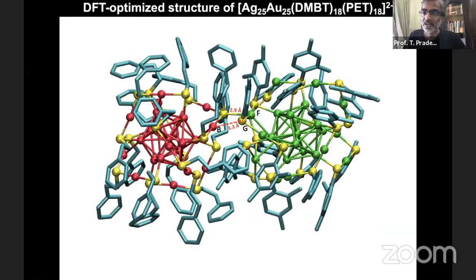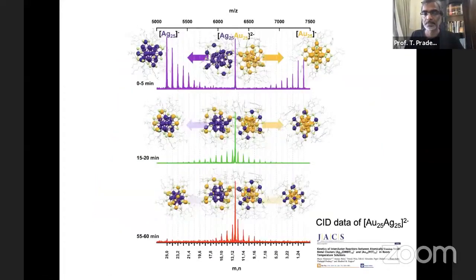You can characterize it. Computationally, you see that these clusters come together and interact, and when they interact, they form specific structures. And in that transition state, you can see atoms moving. Very recently, we found that it is not just that one cluster and another cluster interact, forming products through a dimer. It is also possible that many other dimers form, and they also lead to several products.